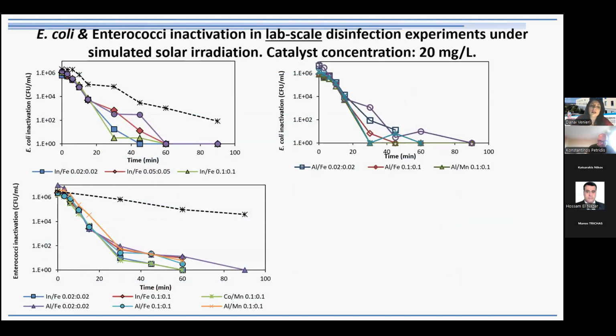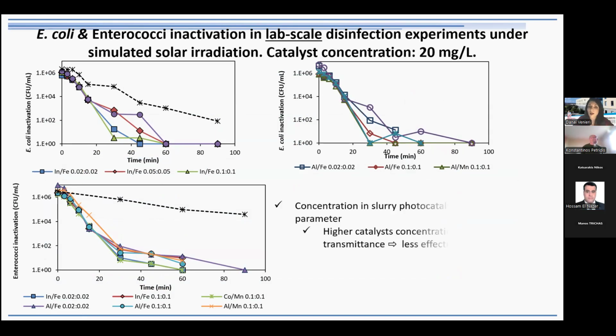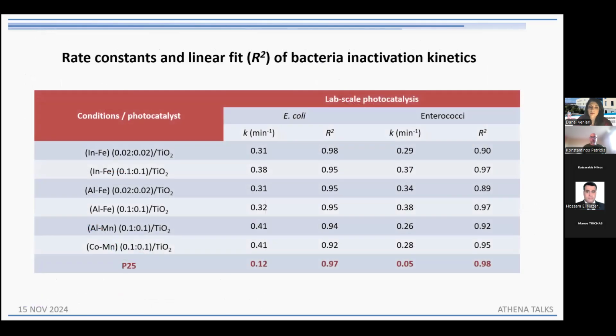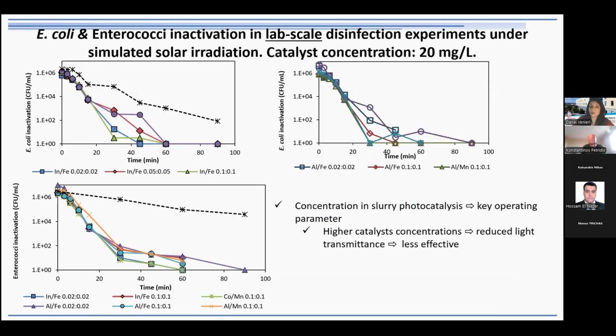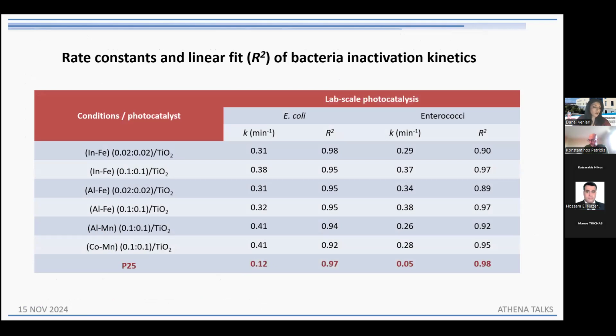Just take a look at the inactivation of E. coli and Enterococci. Those results are from lab scale experiments under simulated solar light. So you can see we could achieve complete inactivation even in 40 or in less than 40 minutes. Again, just to point out the high initial concentration and also the low concentration of the catalyst, 20 milligram per liter. Here you can see the rate constants.